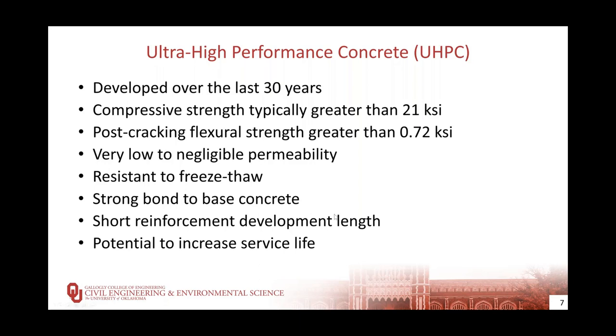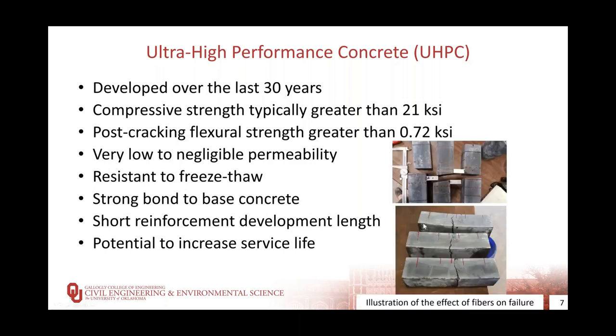But we also get very low to negligible permeability. We get a very high resistance to freeze-thaw, a very strong bond to conventional base concrete, and very short reinforcing development lengths. Combining all these things together, we can get an excellent link slab and potentially increase the service life of our bridges. I have an illustration here of how the fibers change performance. In the top picture, we have no fibers in the matrix. It cracks, it falls apart. In the second picture, they withstood the same load, but the specimens were able to hold together because of those fibers.